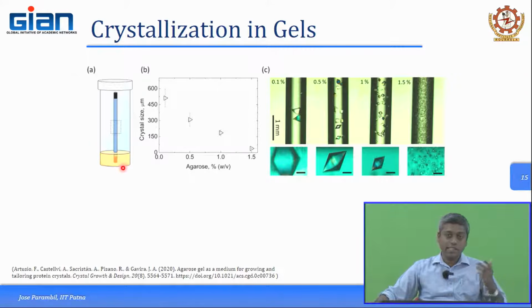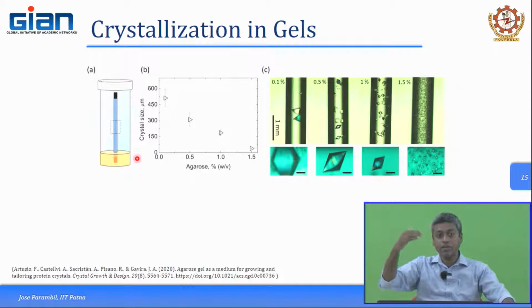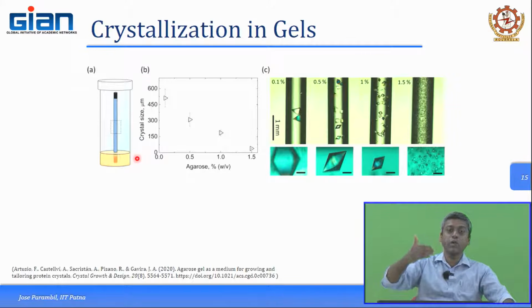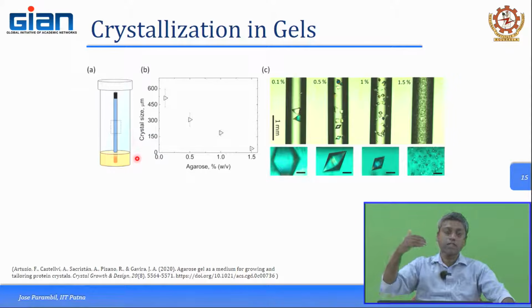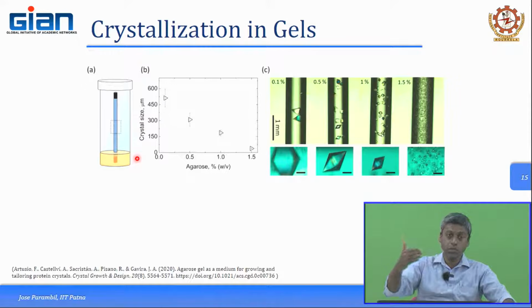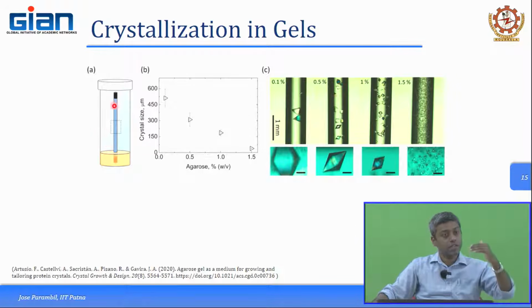Since it is a gel, meaning an agarose gel or something like that, which has quite a lot of water content, but because of the gel structure the liquid does not really move as such. It is by a very slow diffusion that the liquid as well as the salt moves through that. So, that basically creates a very well defined concentration gradient over time within this tubing, and the proteins would start maybe moving in one direction, the salts moving in another direction.